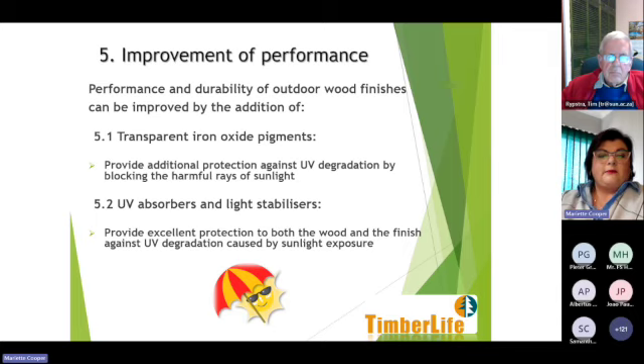In our view, it can be improved by adding one of two things. Firstly, by adding transparent iron oxides and also UV absorbers or light stabilizers. Transparent iron oxides, when added to wood finishes, will provide added protection on the wood surface where UV degradation takes place, by absorbing the harmful rays of the sunlight. And then UV absorbers and light stabilizers are designed and formulated to provide excellent protection, not only to the wood surface, but also to the product itself against UV degradation caused by sunlight exposure. So very briefly, that is my presentation.